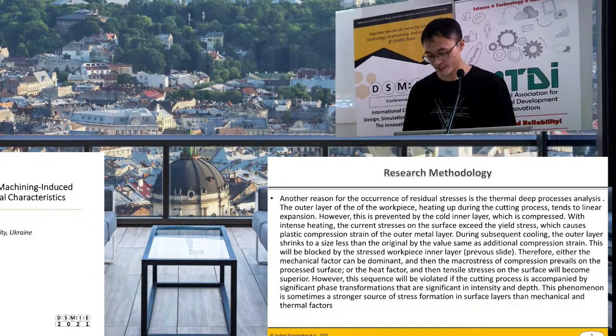And then the cutting process is accompanied by significant phase transformations that are significant in intensity and depth. This phenomenon is sometimes a stronger source of stress formation in the surface layer than mechanical and thermal factors. Next slide, please.